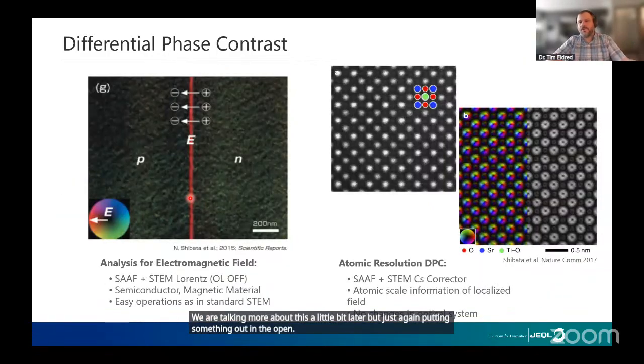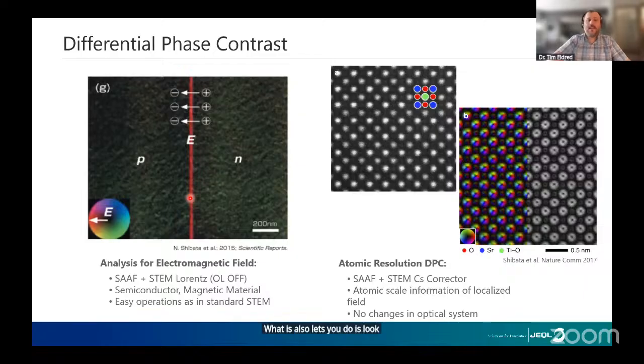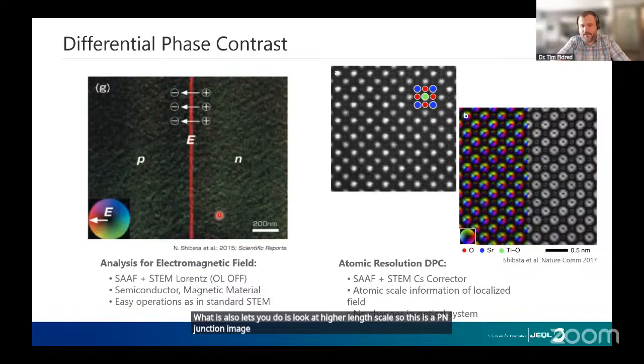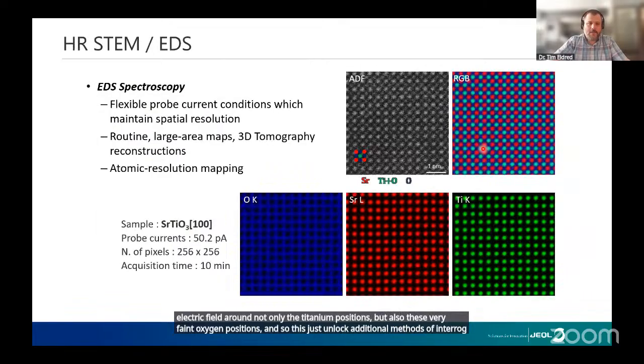What this also lets you do is look at higher length scale. So this is a PN junction imaged with differential phase contrast, showing the direction of the field at the PN junction. Additionally, here's an atomic resolution image where you can see the electric field around not only the strontium and titanium positions, but also these very faint oxygen positions. And so these just unlock additional methods of interrogating your data.